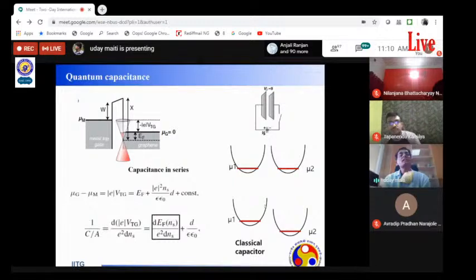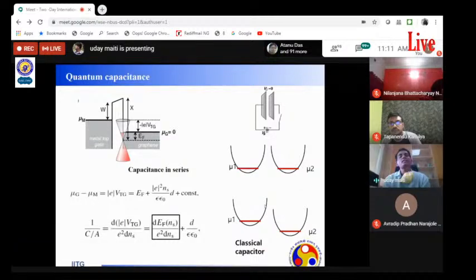But in the case of graphene, on one side the density of states is low, so you can think of that one side, the graphene side, as just a measuring cylinder, and the metal is just like a water bucket. So if you take 50 ml of water from the bucket and give the same amount to the cylinder, the water level in the cylinder will change a lot. So it is related to the fact that the density of states of the graphene is low near the Dirac point, and this gives rise to the change of its intrinsic chemical potential.